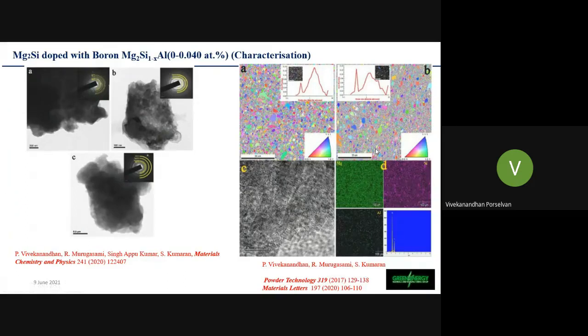And coming to some case studies. This is one of the silicide materials, called magnesium silicide, that is doped with boron and doped with aluminum of varying concentration. If you look at the milled powders, we can understand that the powders are very, very fine, on a scale of less than 30 nanometers.